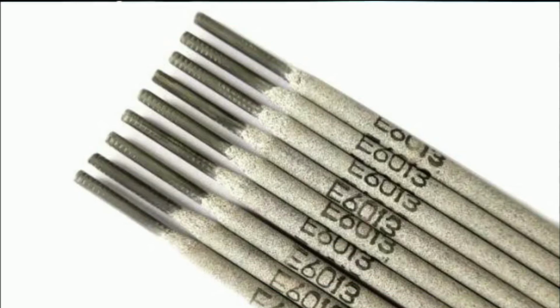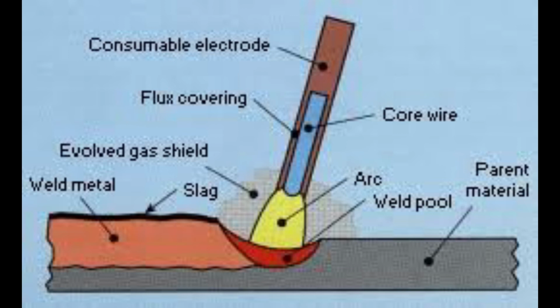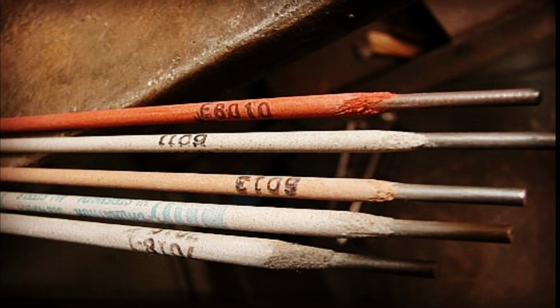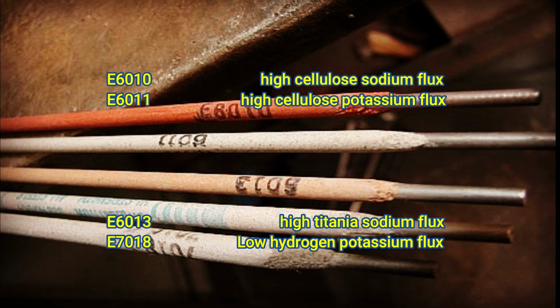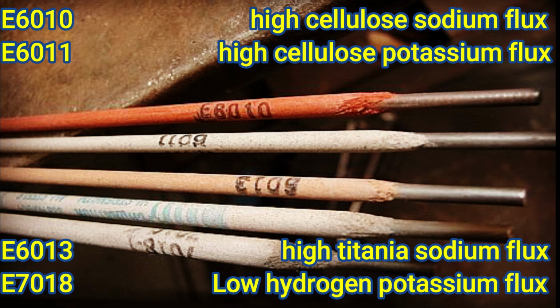So during welding, when high current passes through the electrode, which tends to melt it, flux density being less than the metal, it floats on top of the molten weld pool, which prevents the weld from contamination and oxidation, which will result in formation of welding defects. So here are few examples of flux which you all can see on welding electrodes, which are generally used in industries and fabrication purposes.